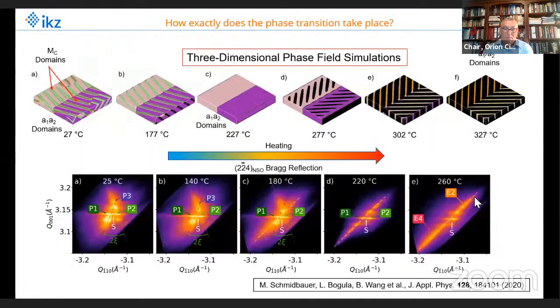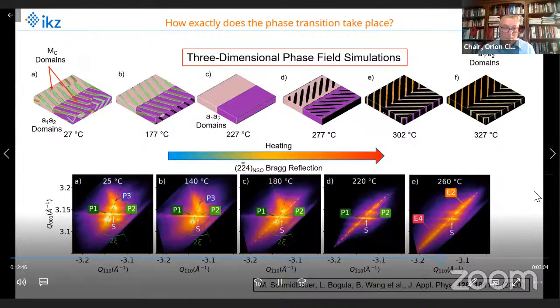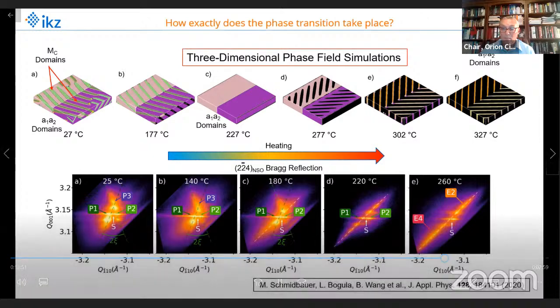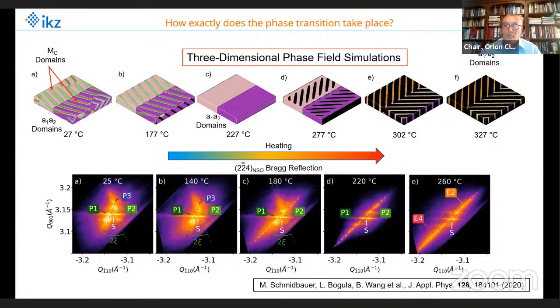But how exactly does the phase transition take place? For that reason, I'm showing you a true temperature series between room temperature and about 260 degrees centigrade. On top you see the phase field simulation, and at the bottom you see the corresponding X-ray data. We start at the top left, where you see the simulated domain pattern with the A1, A2 and MC domains. This is reproduced in the X-ray data. You see the peaks P1, P2 coming from the A1, A2 domains, and you see the peak P3 originating from the MC domains. When you heat up the sample a little bit, nothing serious will happen.